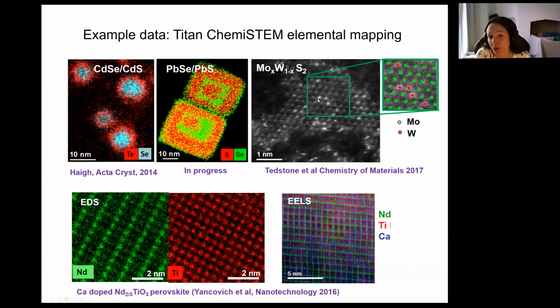The sort of images that you can get from these materials are just some examples from our electron microscope, the Titan. You can see here for this molybdenum disulfide nanosheet, we can just see the positions of the metal atoms, but some of them appear brighter, and that's where the molybdenum disulfide has been doped with tungsten. So there we can identify the positions of the tungsten atoms and see that this nanosheet is really fully alloyed. If we look then at more robust materials, in this case oxides, we can use both the X-ray imaging and the electron energy loss spectroscopy to build up a compositional map of the positions of the atomic columns. If a material is a bit less robust, which is typical of the sort of nanoparticles that we look at, then the elemental mapping resolution tends to be of the order of more like 1 nanometer rather than atomic resolution. A couple of examples of elemental mapping in different nanoparticle systems are shown up here.